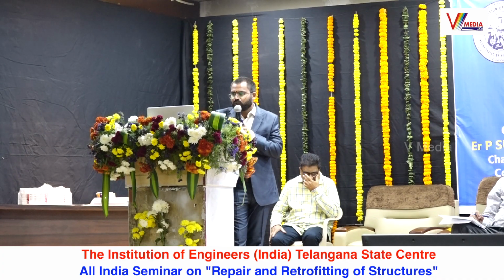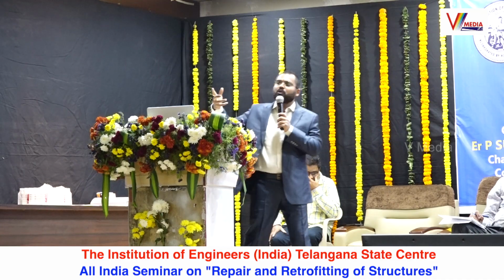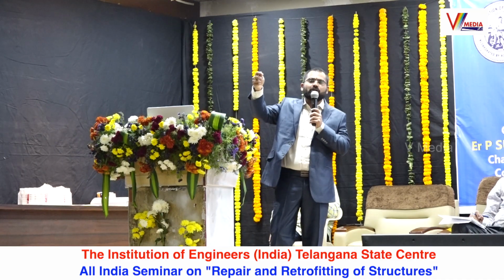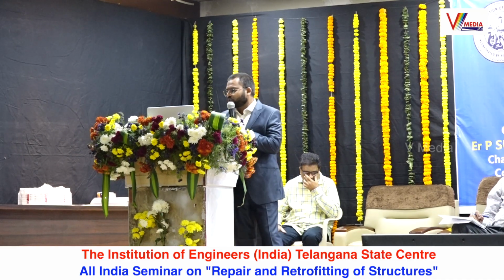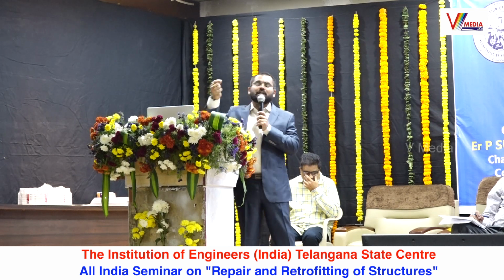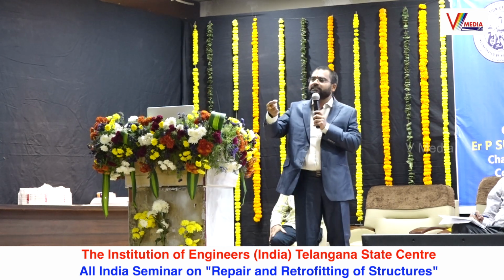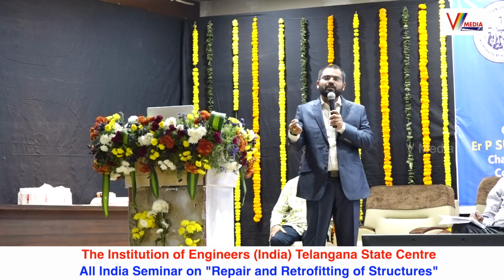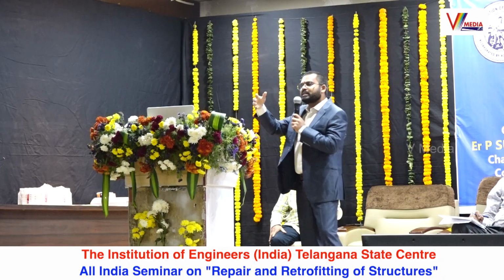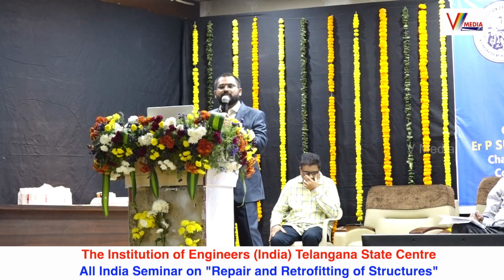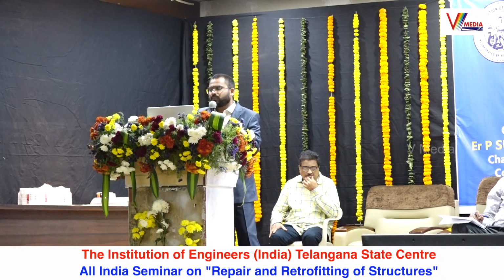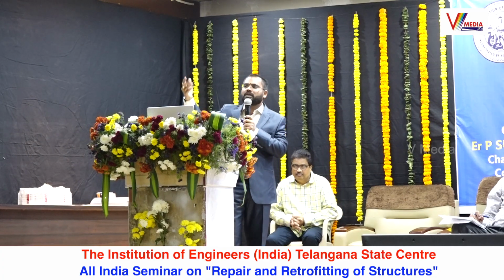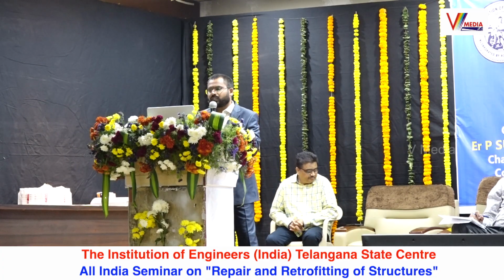I'll show you. Now, how do you measure carbonation? You can chip the surface concrete, spray a phenolphthalein solution, and see the change of color in the concrete. If the concrete changes its color to red purple within 30 seconds, then the concrete is good. It's not carbonated. If there is no change in color, it is said to be carbonated. Then you have to do concrete petrography to understand the further problems.